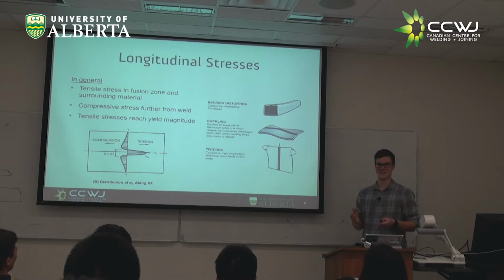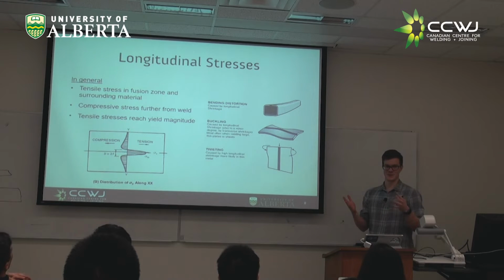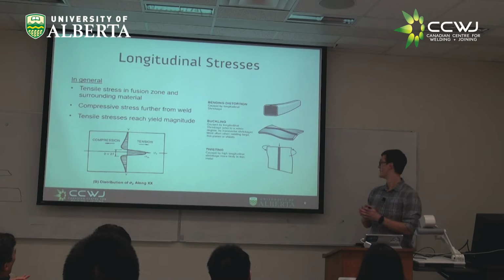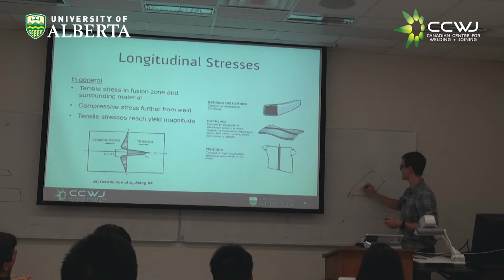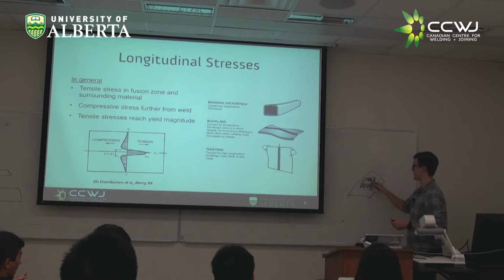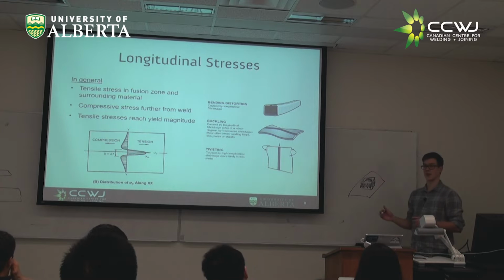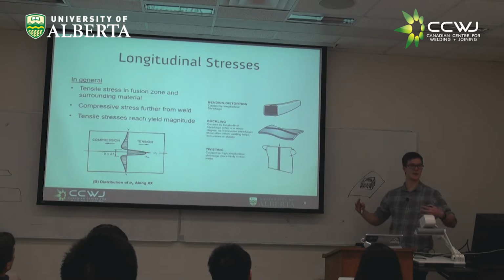And what's happening is as you put subsequent layers on top of the earlier layers, they develop longitudinal stresses. And one of the ways they try to reduce the effect of those stresses is to keep the whole print hot. So if you have your build plate for your 3D print, and you're printing something that's building up layer by layer until you end up with this structure where you have walls. If you imagine these are outside walls and a hollow interior, each of these layers is going to have some longitudinal stresses, some shrinkage. Now to minimize those stresses, they minimize how much it can cool.